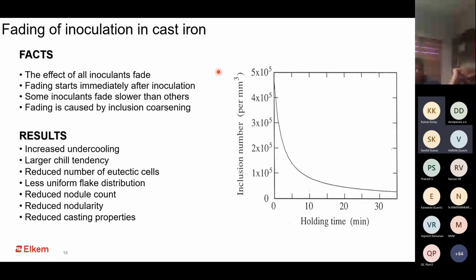So at times we have seen the nodularity being poor in a casting, and we have tried to solve it by improving on the inoculation. And that has worked. So nodularity as such is not only dependent on the ferrosilicon magnesium that you add, it also depends on the quality of inoculant that you add. And of course, if you end up with all these problems, eventually the property of the casting is also going to get reduced.